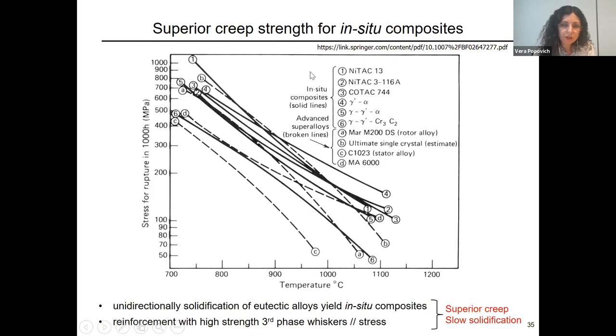They have specific names. So these composites are the solid lines shown here. In broken lines, it shows the advanced superalloys. And you see the difference between the two with respect to the stress for rupture in 1000 hours. The composite materials have more superior properties. They use unidirectional solidification of eutectic alloy, yielding this kind of in situ composites.